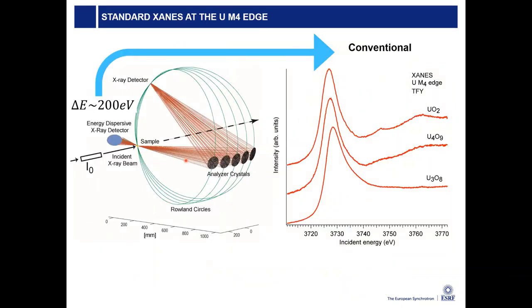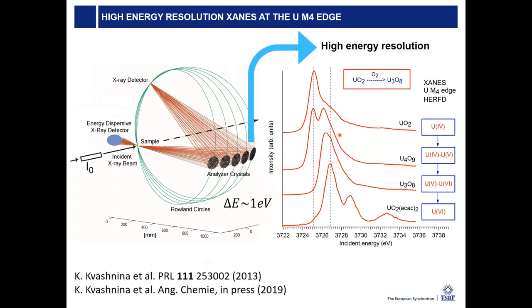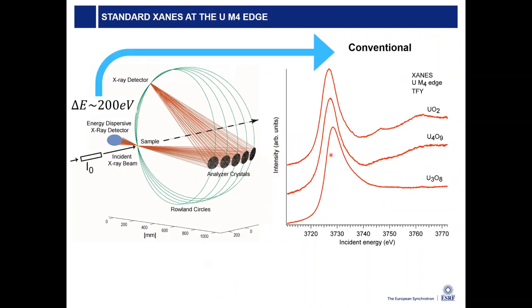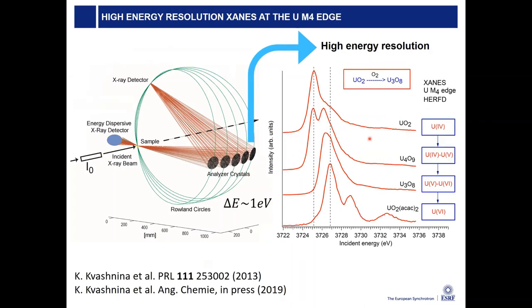Another example here, just to show you can also do this in the tender X-ray range. This is uranium. This is the M4 edge of uranium. If you measure it conventionally, you get the red lines here. If you measure high resolution, you can suddenly resolve all the spine structures. These are the same samples, low resolution, high resolution. And this really allows you to distinguish in mixed valent compounds. So you have uranium-4 and uranium-5. You can distinguish between the two in the high resolution data.